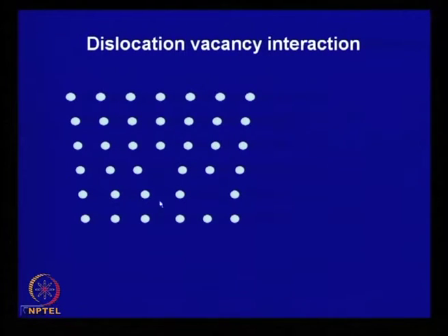So, now this is the gap. Now, if there is a vacancy in the lattice here, depending on the temperature, it has some mobility. It does not remain stationary; it keeps moving through the lattice at random. Suppose the next step it comes here, and it might as well come here as well. That will be a very stable configuration. In that case, what is happening is that this edge dislocation has moved up. This is called a climb motion of a dislocation.